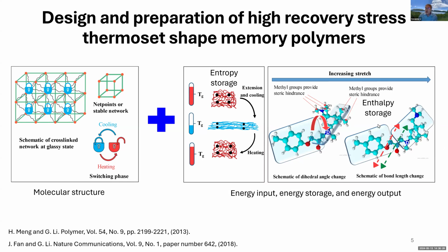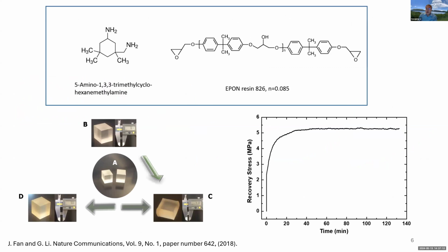Another mechanism is enthalpy storage. Basically this one is through chemical bond length change and bond angle change. If you recall the Gibbs free energy equation, you will see that, of course, both entropy and enthalpy are able to contribute to energy storage. Actually, we rely more on the enthalpy storage. The reason is that in the past, people basically relied on entropy, and the recovery force, or the stress, is very, very limited. So we proposed the idea of enthalpy storage.